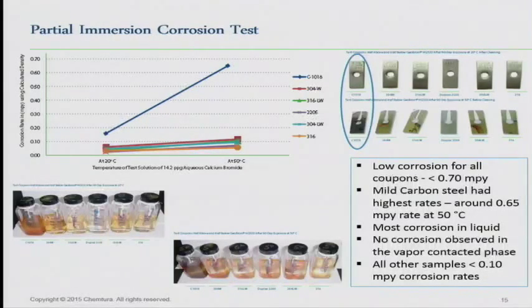So you can see the solutions did pick up some color, and there was some surface corrosion evidence on the coupons. But for the most part, if you have a tank that you're using that's stainless, or you can even use lined tanks, lined FRP, things like that, as long as they can handle the density of calcium bromide, you don't have an issue. When you're adding it to your belts and things like that, even your metal shouldn't be seeing too much of an impact.